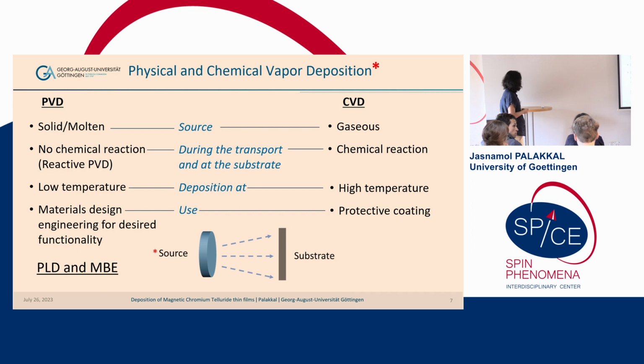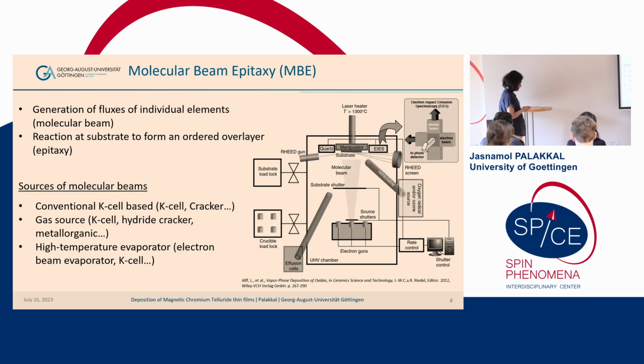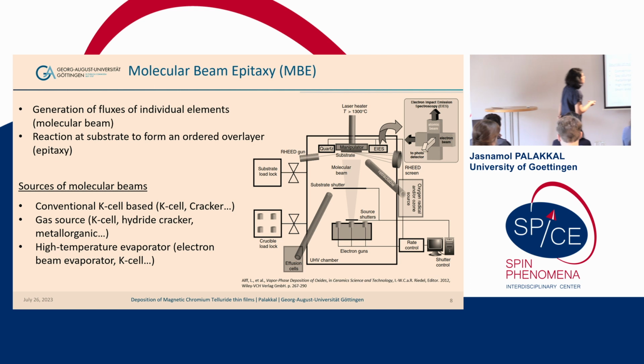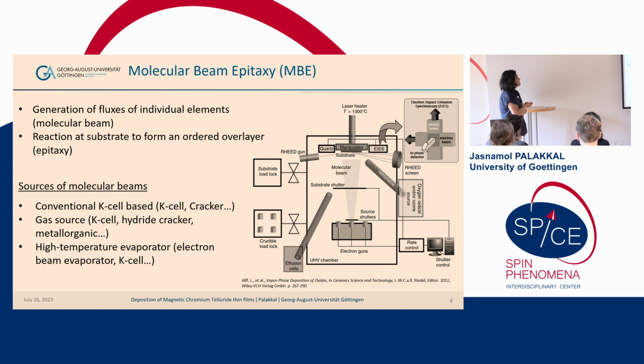And if you want to modify the material's property by changing fine structure or electronic structure, it's better that you use a physical vapor deposition. And pulse laser deposition and molecular beam epitaxy come under physical vapor deposition techniques. So here is the schematic of a molecular beam epitaxy. Here you can also see an oxygen inlet. This is what makes the system an oxide MBE. Oxide MBE is also known as a reactive MBE because not all the UHV parts are compatible with the reactive gases. So you need special UHV parts if you want to grow oxides in an MBE.